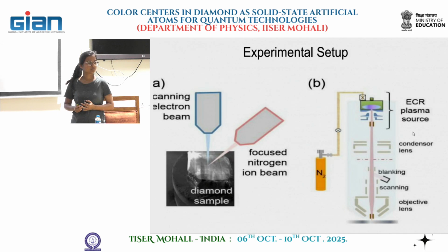And if you now go to a smaller hole, unfortunately, you do not couple the plasma out very efficiently. So at one point, basically, the resolution of that machine cannot go below 50 nanometers. That's the technique. But 50 nanometers is already quite nice, and you can also do